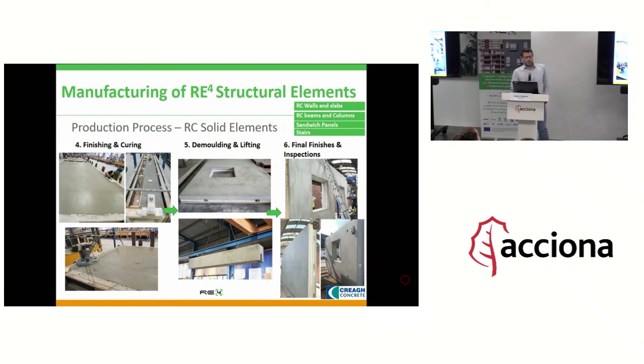Once the concrete has hardened enough in the molds, the finishing works can start, and they can be done manually or mechanically depending on the project specifications. Then the elements are left to cure until they reach the minimum required strength for lifting, which in this case is 15 megapascals, and usually happens within the initial 16 hours.